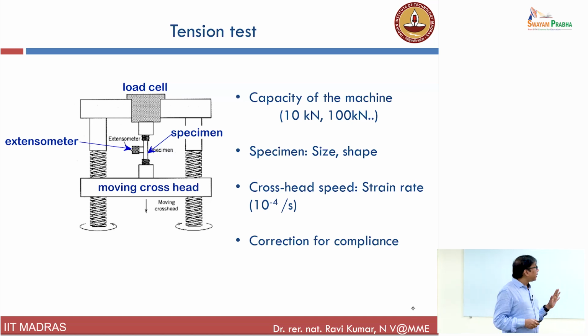And the typical strain rate that you have to use is something like around 10 power minus 4 per second. If you don't do that, you are not really getting the right result. And again, the biggest challenge is when somebody does a tensile test, I ask them, did you do compliance correction? And many of them are blinking. They don't know what compliance correction is.